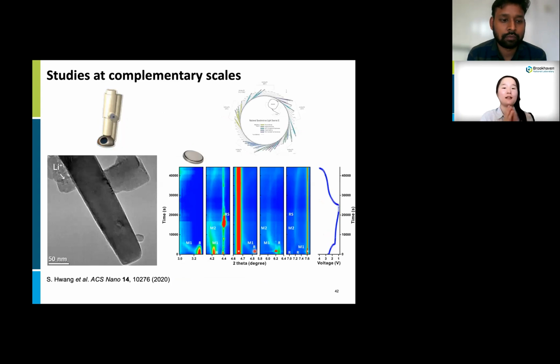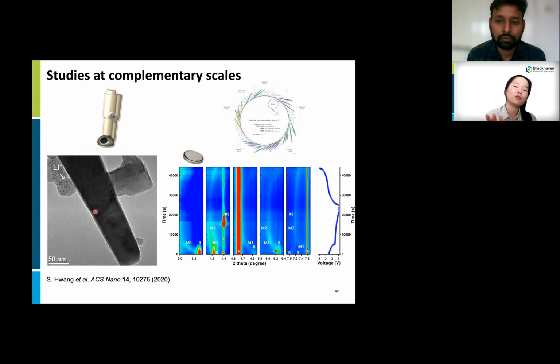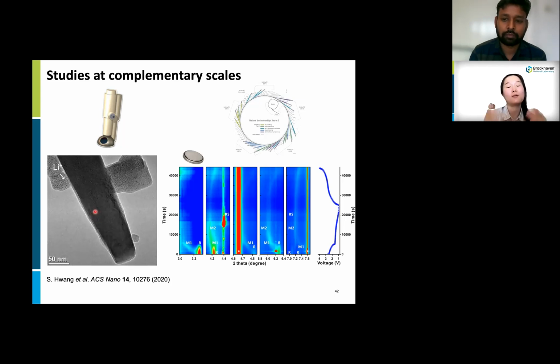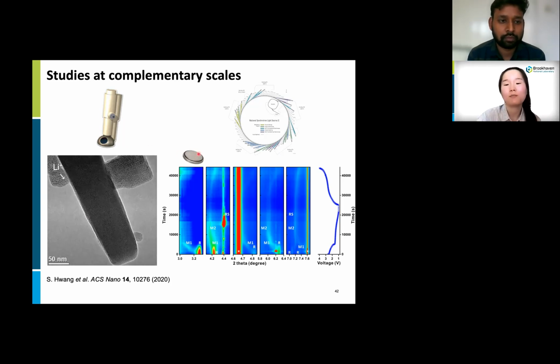So for example, lithiation mechanisms can be explored at complementary scales. Here I have iron cobalt oxyfluoride nanowires, and inside the TEM, we can clearly see how the morphology of the nanowire is changed with lithium. In the meantime, I can make a coin cell with the same material, and I can get X-ray diffraction patterns while testing the batteries. So by combining synchrotron X-ray-based techniques and transmission electron microscopy, we can obtain a more complete story about the phase evolutions in electrode materials based on the electrochemical tests.